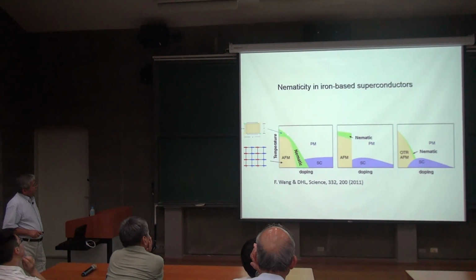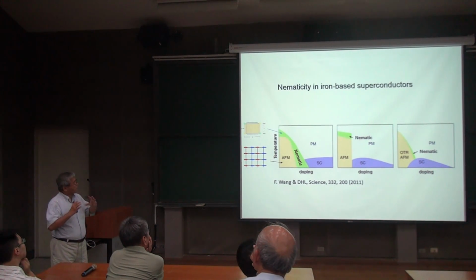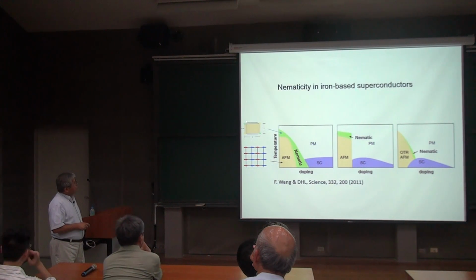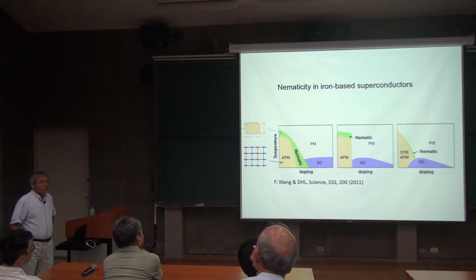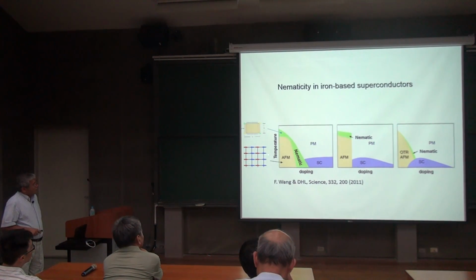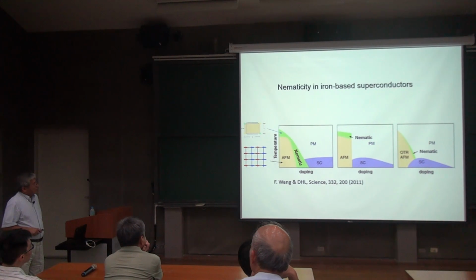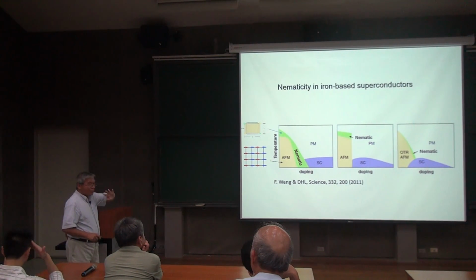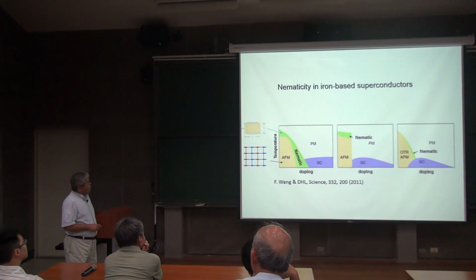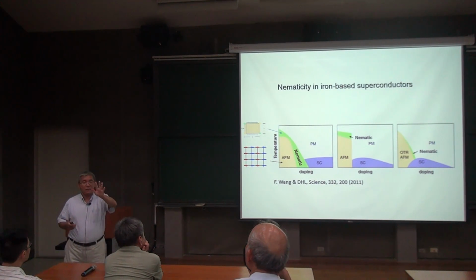In this green region, what happens experimentally is that the lattice structure spontaneously distorts. Originally the lattice has a square symmetry, but after the spontaneous distortion, it has a rectangular symmetry. Very interestingly, this lattice distortion doesn't break any spin rotation symmetry. By spin rotation symmetry, I mean rotating the direction of the local magnetic moment, because the antiferromagnetic order has been lost once we enter the green region, but yet this region has a different symmetry breaking. It destroys the crystal 90-degree rotation symmetry, not spin rotation, okay? Crystal rotation is different from spin rotation. So if the crystal spontaneously distorts from a square to a rectangle with the long axis in the x direction, it obviously has broken the 90-degree rotation symmetry.